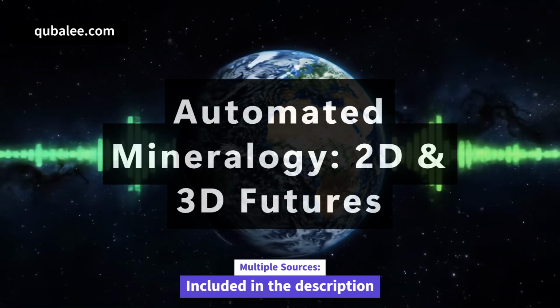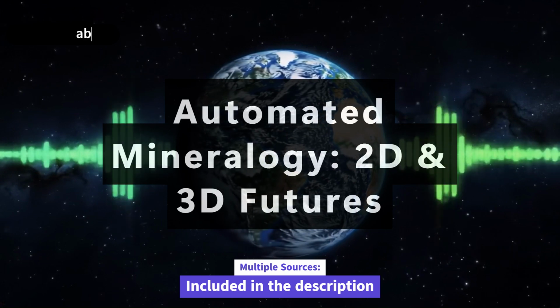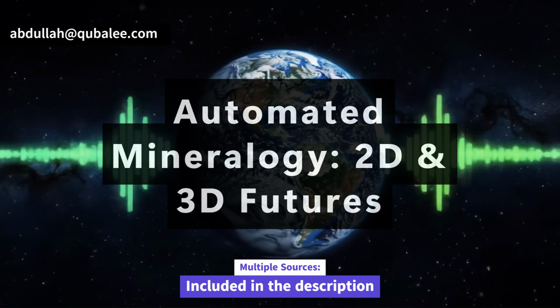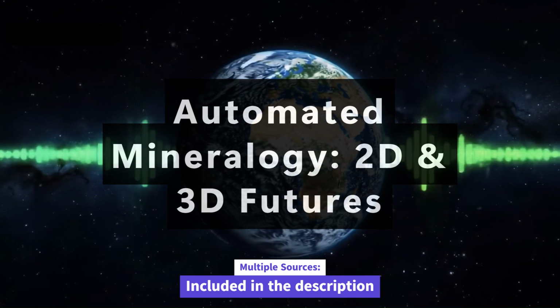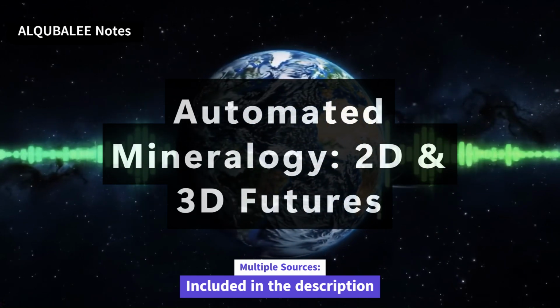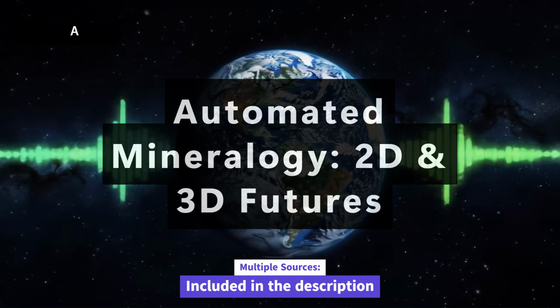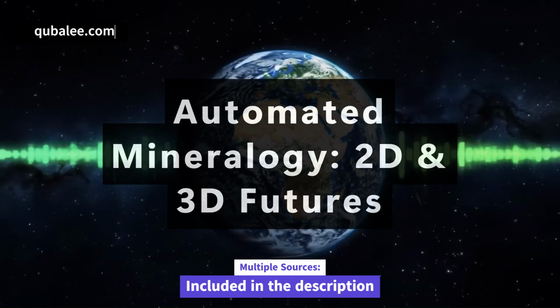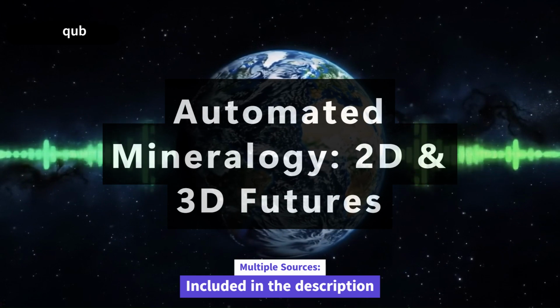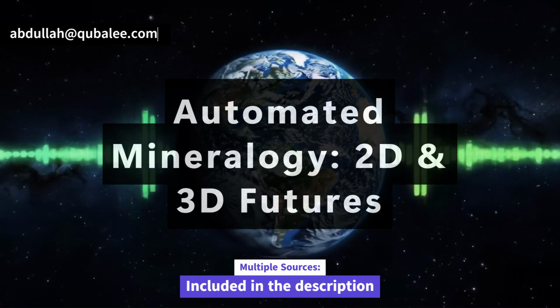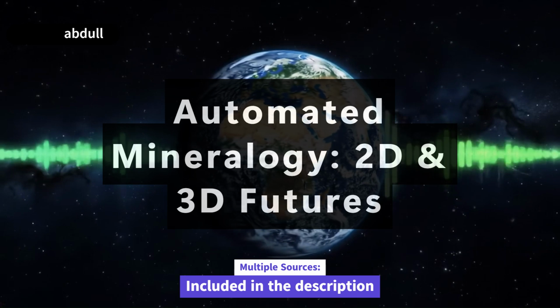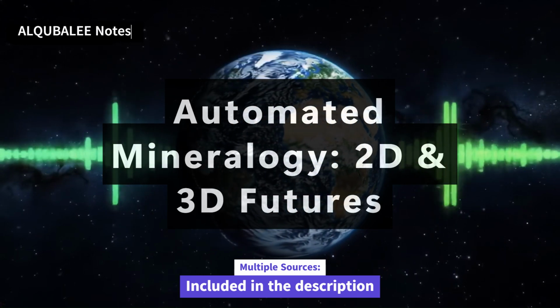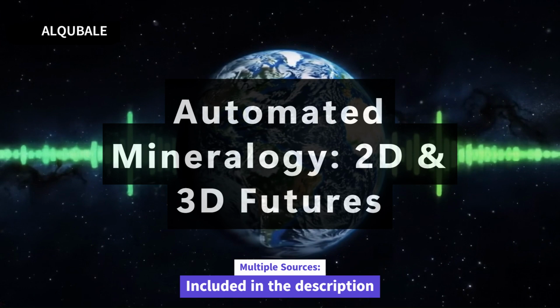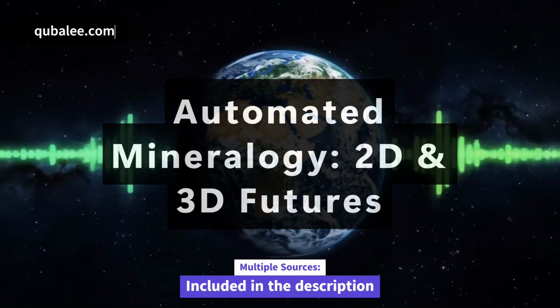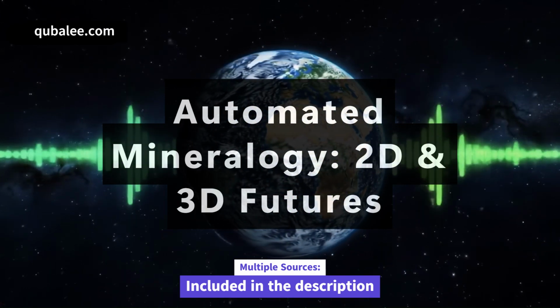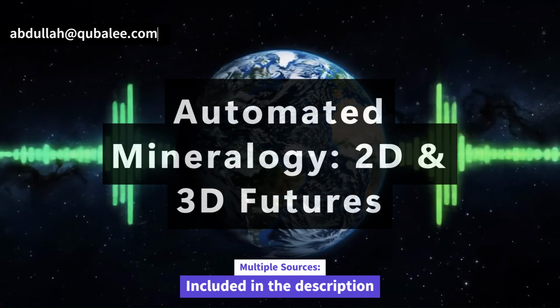And because you have this quantitative chemistry linked spatially to every pixel, you can visualize it too, right? With those special maps? Yes, the hybrid maps. They're really powerful visualization tools. You essentially overlay the quantitative elemental data directly onto the mineral map. So you see the mineral map, but colored by, say, calcium concentration. Exactly. You could see, for instance, a garnet grain on the mineral map, but the colors within that grain show you how the calcium concentration changes from the core to the rim. That zoning can tell you about changes in pressure or temperature the rock experienced as the garnet grew. So you're visually mapping the chemical history within the mineral.